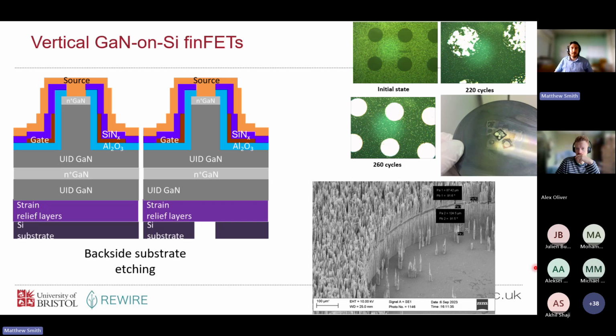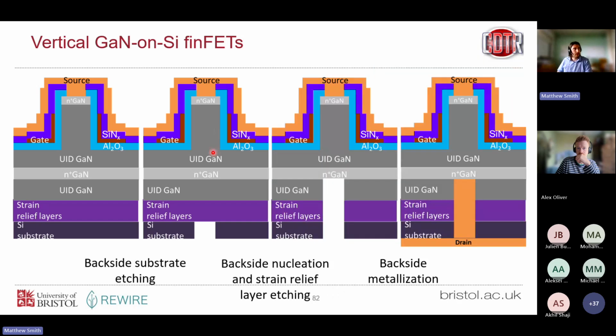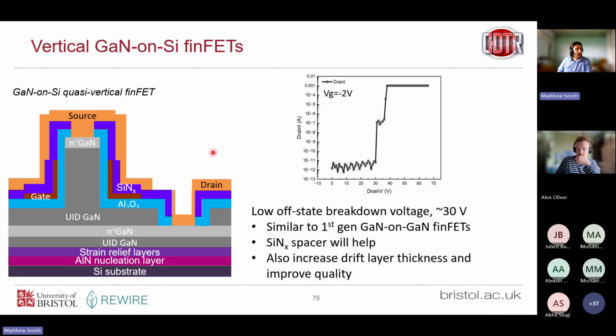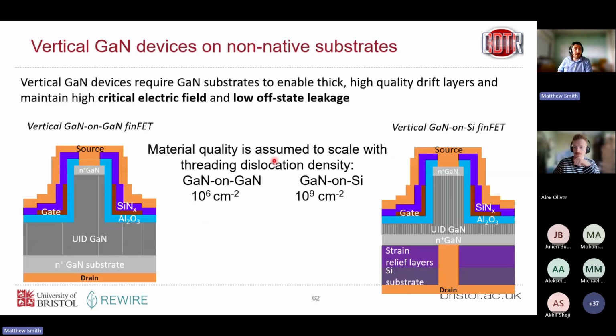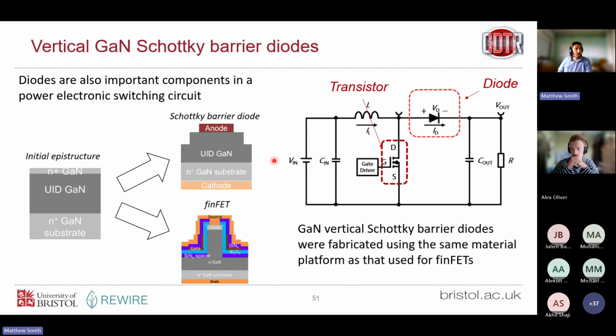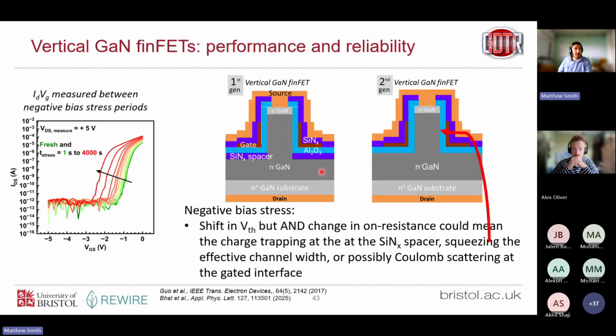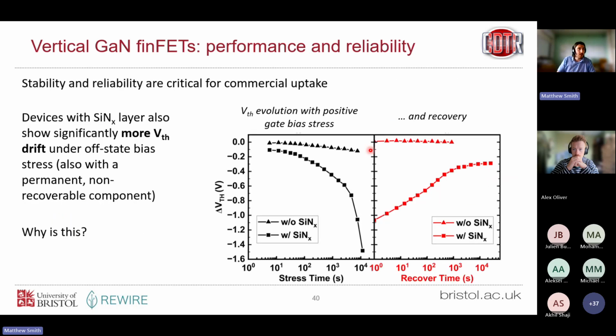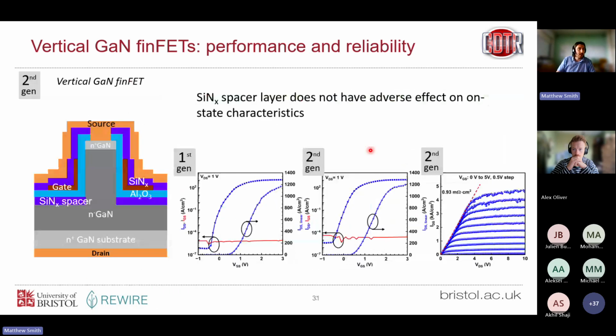It's all going through the fin and then down through the layer here, through our bulk drift layer. In terms of mobility degradation, there probably is some. So if I go back to those schematics, if my slides are going to let me, it's difficult to say because measuring the mobility on those fin sidewalls is quite tricky. And in fact, measuring any property directly on these fin sidewalls is quite tricky. So we can model them and we can look at the changing output current, which seems to be minimal. So it suggests it's certainly not a showstopper. This is the first generation output current, not much difference within statistical variation.